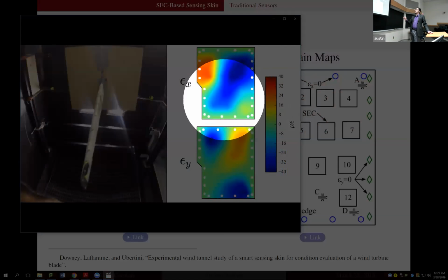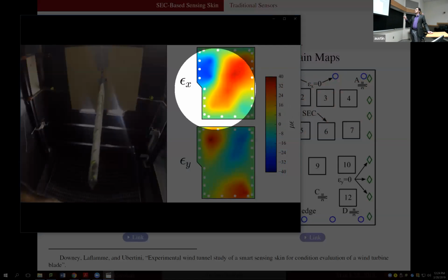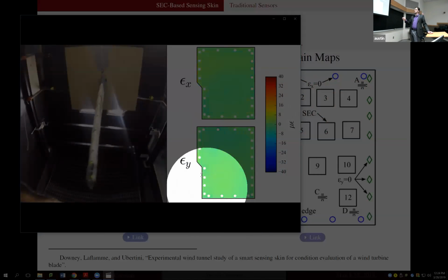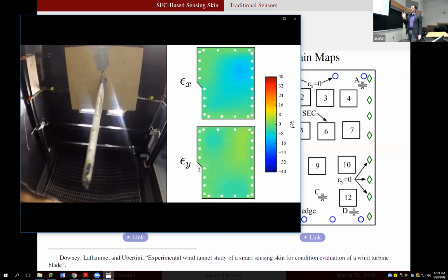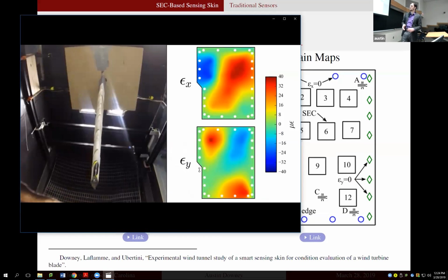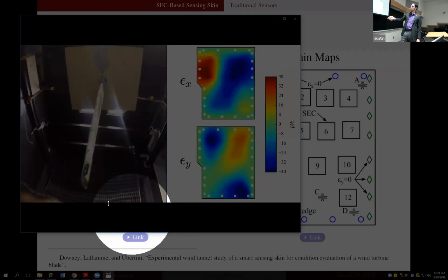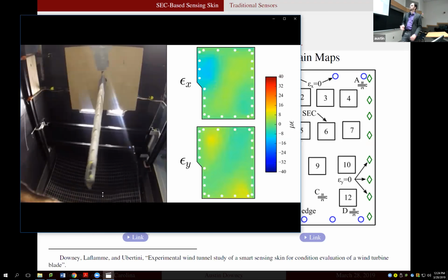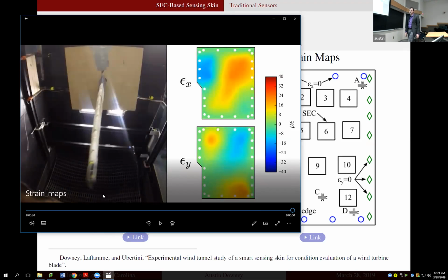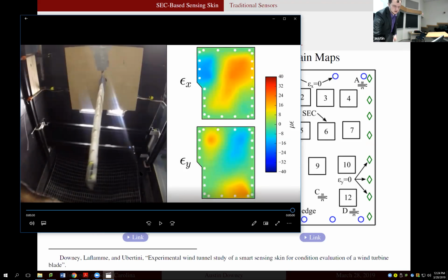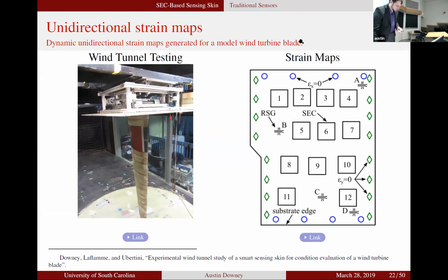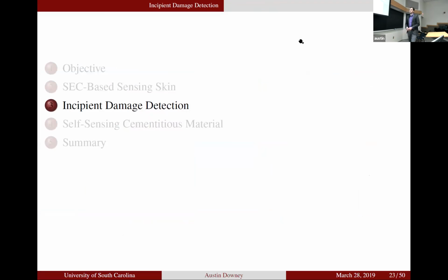But what you'll notice from the x and the y is you get tension and compression right next to each other, and this shows that there's a moment, there's a torque in the turbine blade, and you can see that twisting in the tip of the blade if you watch. The SECs are able to pick up that torsion in the blade through a full field strain map. So they work really well for large scale structures, for monitoring very easy to detect cracks.